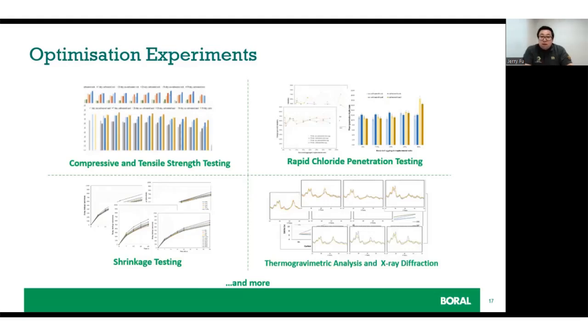We use thermogravimetric analysis and X-ray diffraction to perform the initial analytical analysis to see the effectiveness of the carbonation reaction and compare rates of carbonation reactions. We use our in-house carbonated recycled aggregates to conduct concrete trials to investigate the performance of our products at various natural aggregate replacement levels. So far, our preliminary results have shown to be in alignment with reported results from the literature. We're still doing more experiments, working to optimize the carbonation parameters further to maximize the CO2 uptake of the recycled concrete aggregates to help us push the limit of replacement boundaries.